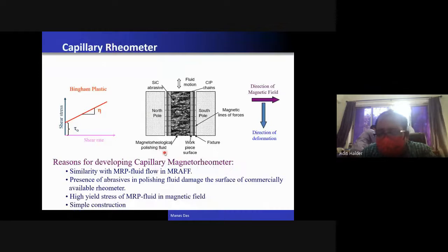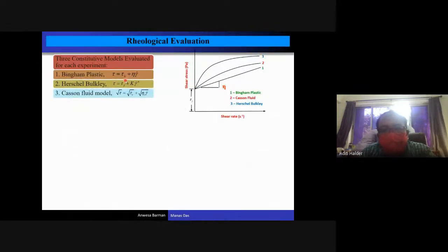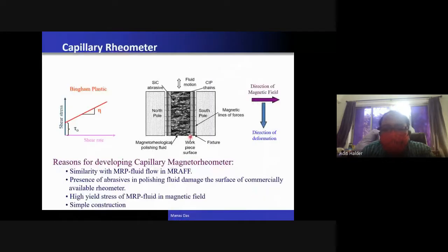Now for measuring the yield stress and viscosity, there is a capillary rheometer. Through this capillary, the MR fluid is forced to flow. This capillary diameter is around 2 millimeter.